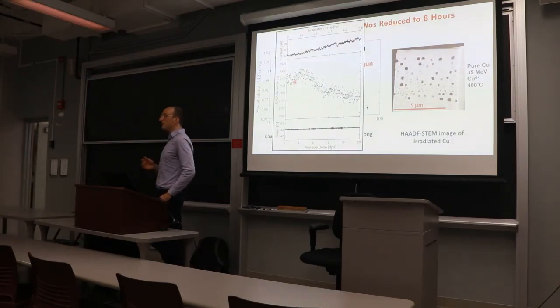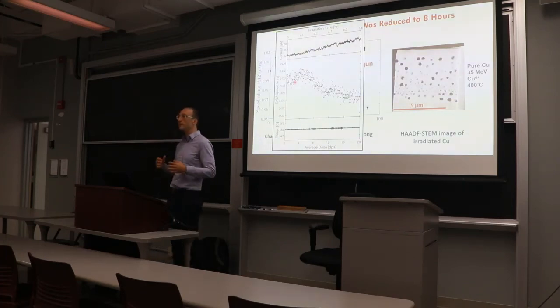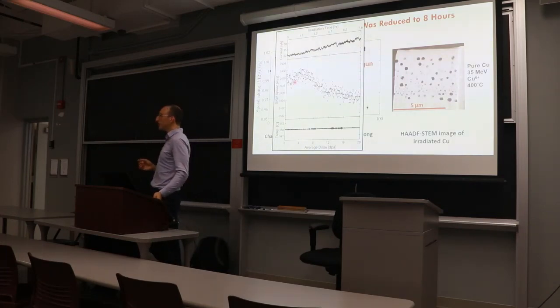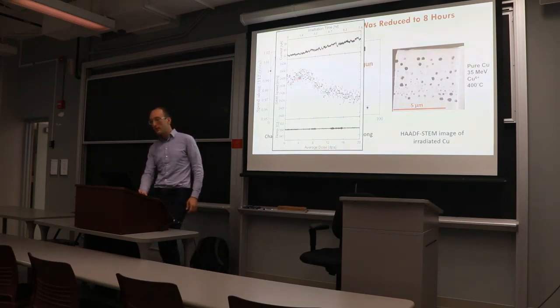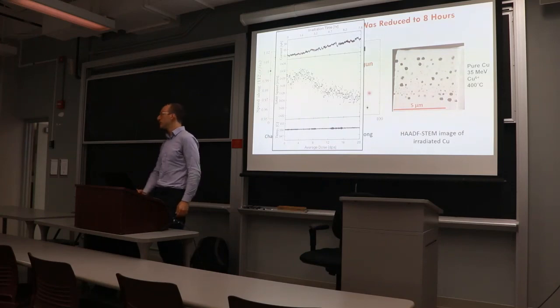When you do this on unirradiated materials that have suffered cold work, the dislocation density increases at the same rate that the pinned segment length decreases as well. The two effects cancel out. But when you add radiation to the mix, you pin those segments and you see an increased stiffness from an inability of those dislocations to bend. And so on materials that void swell at a higher dose, we actually see a saturation and a level off due to dislocation hardening, and then a drop when the void swell expands. So we can see the kinetics of that only during irradiation, not during less extreme environments.